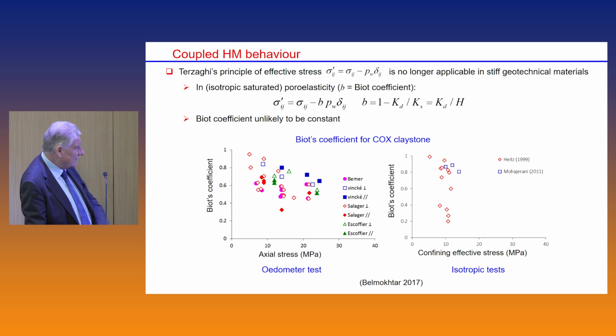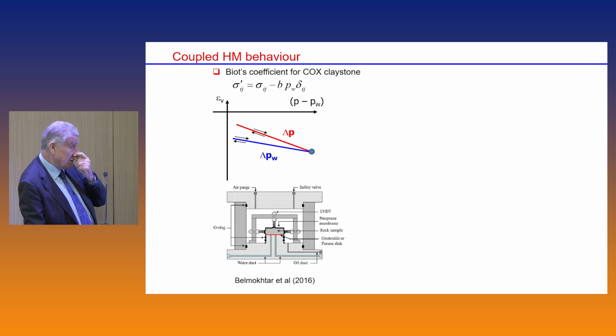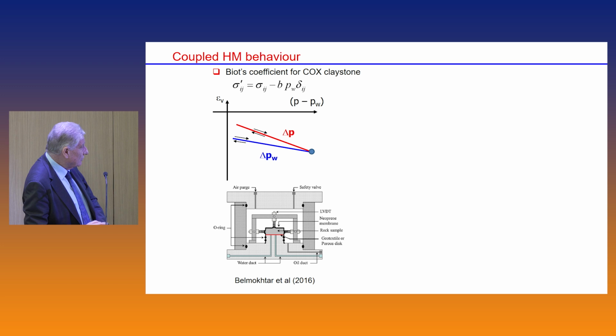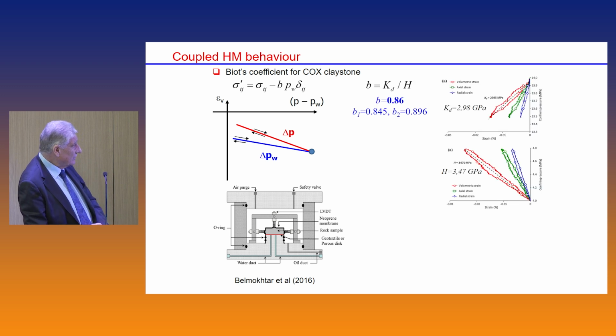There has been quite a bit of clarification on this by the work done at Cermes, in the group of Pierre Delage and Jean Sulem, in which they try to measure very carefully the Biot coefficient for the Callovo-Oxfordian claystone. They did that in the traditional way, in which you apply a cycle of mean stress, you apply a cycle of pore water pressure, and if Terzaghi holds, they should give the same result, but it doesn't, and so they found in this particular case values around 0.86.